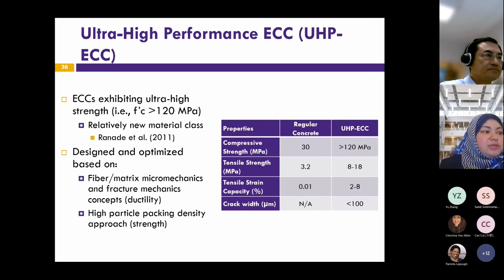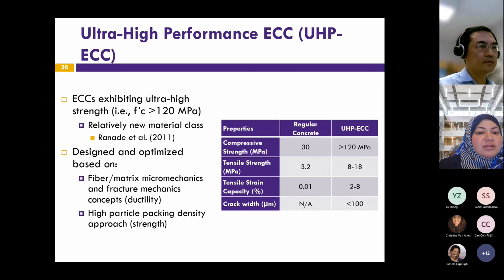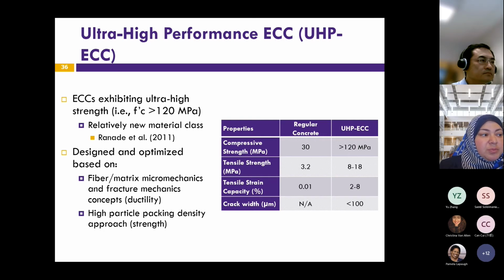Okay, so ultra high performance ECCs. What is the definition of ultra high performance ECC? It can have an ultra high performance compressive strength of more than 120 megapascal. Here, this table also summarizes the properties that we are expected to get. So we want a compressive strength of more than 120 megapascal, a tensile strength of 8 to 18 megapascal, a tensile strain capacity of 2 to 8%, and small crack widths, of course, under 100 micrometers.